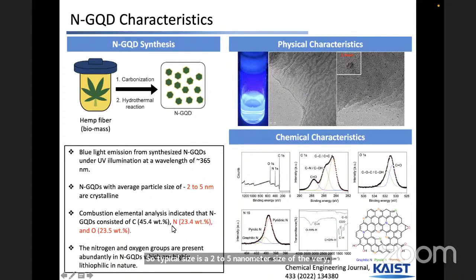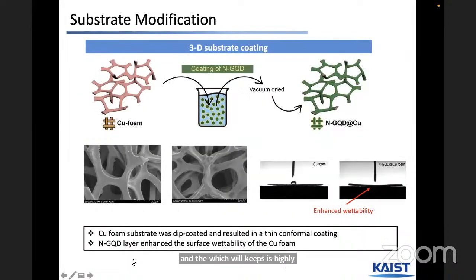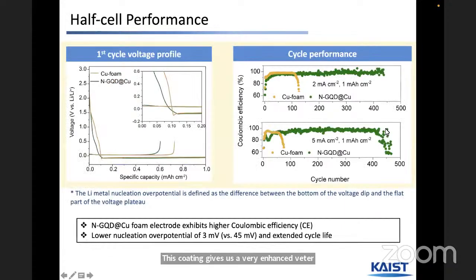Typically nitrogen is almost 20 weight percent, and oxygen is 23 weight percent. The nitrogen and oxygen groups are present abundantly, which gives us a highly lithium-philic nature. So we just dip, and then we can get a very well coating on that. This is a nicely coated one. This coating gives us very enhanced wettability as well, so it is easily coated on this.